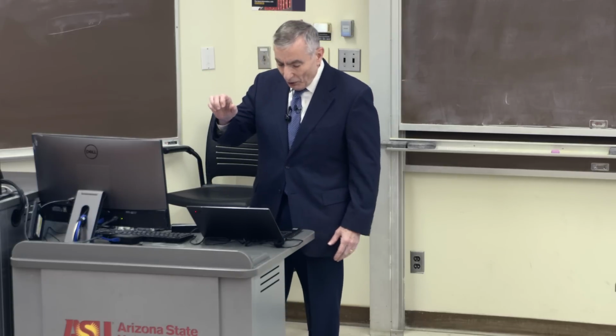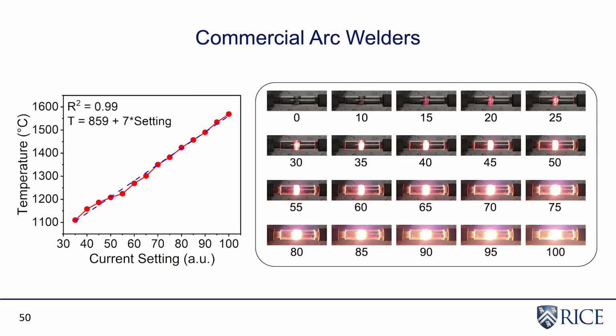And what we found is you can just take the arc welder and go to the current setting, which is not really a direct current setting on the arc welder, but it's close enough. And just by turning the dial, you increase this, you get about these small increments. So as you start increasing the dial, you can dial in the temperature. Here's 1100 degrees up to 1600 degrees. So you can either use a high temperature flash or run it a little bit longer with an arc welder. And as you dial this up, the material just starts heating higher and higher.